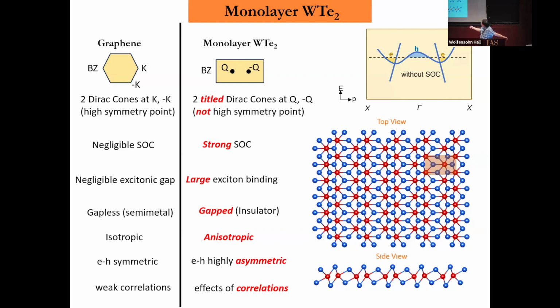So the list of differences: from the Dirac cone view, you already see the tilted Dirac cone. In graphene there's no spin-orbit coupling, it's negligible. Here there's very strong spin-orbit coupling because it's a TMD material. And in graphene there's also negligible excitonic pairing potential - here it's very strong, again because it's a TMD material.